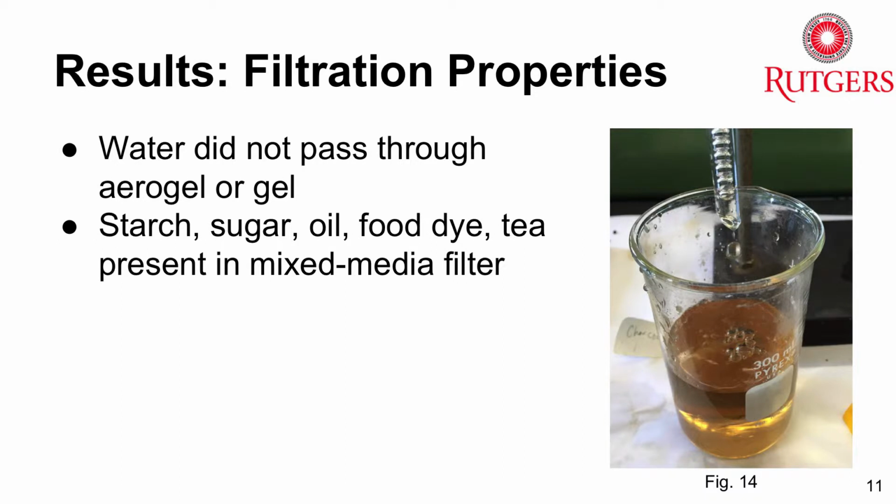Our general results for all of our experiments were that water did not pass through either the gel or the aerogel. Also, starch, sugar, oil, food dye, and tea were all present in the filtrate of the mixed media filters that we tested, which means that, at this point, they cannot compete with commercial popular water filters.